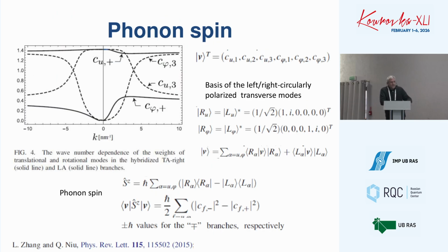It should be noted that micropolar theory gives truly chiral branches of excitations. In contrast to theories based on the displacement only, where definite chirality appears only in some parts of the Brillouin zone and depends on the k vector, here, whatever the k vector, we obtain only definite chirality.